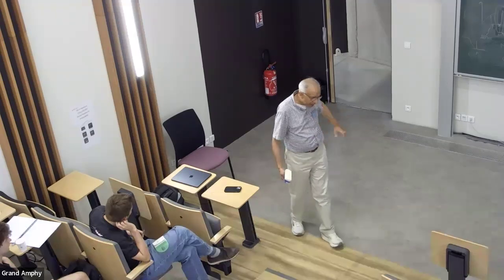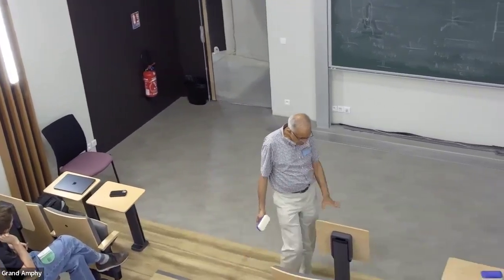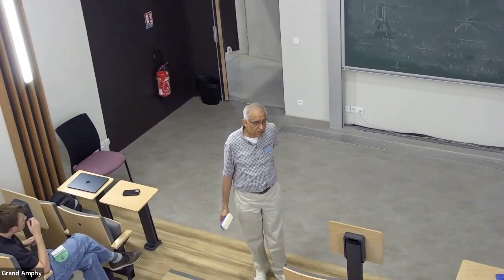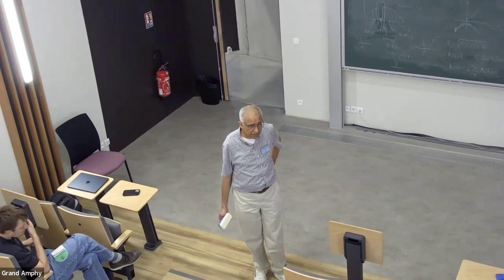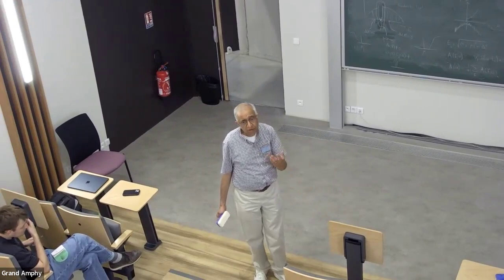No, because you're just adding this by hand. I think it's a fair statement to say that if you're in the superconducting state, a Cooper pair lives forever. I don't think it's the lifetime of a Cooper pair. Maybe if you're just about Tc and talking about the sort of fluctuation physics that Andre Lama was talking about, then there you can talk about lifetime of Cooper pairs and so on. But the lifetime of Cooper pairs is infinity. But somehow it's the Bogoliubov excitations. The question is how much of that is in.